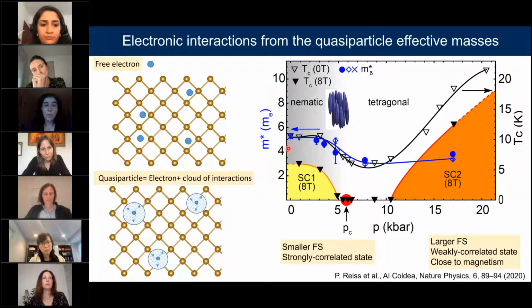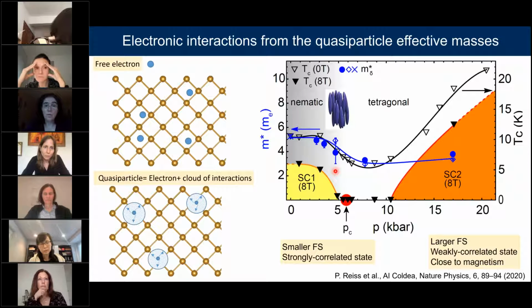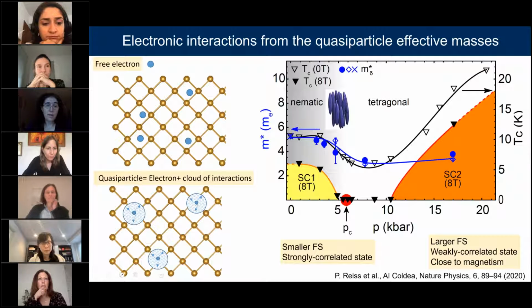From quantum oscillations, we can probe what happens to electrons inside the material and detect their effective masses, which tells us about the effect of electron correlation. These masses are very heavy, for example, inside nematic phases, but they change a lot as superconductivity changes. This information is very important to understand the ground state of these materials before they start becoming superconducting. As an example, in a simple metal, we expect the electrons to have an effective mass of 1, but in the presence of electronic correlations, these electrons become quasi-particles, and their heavy mass reflects the cloud of electronic interactions.